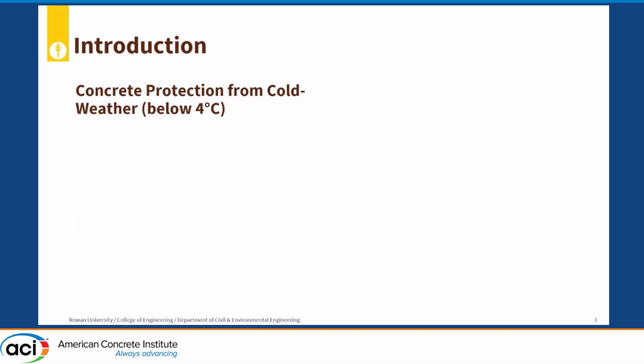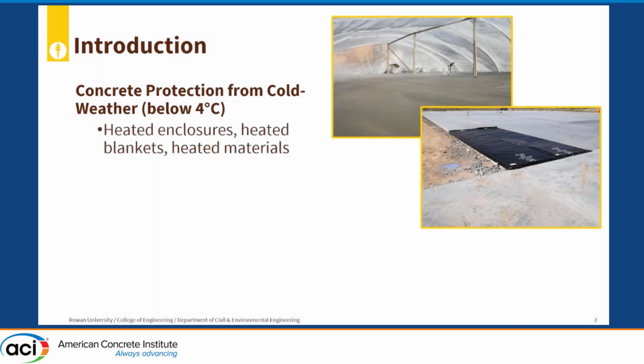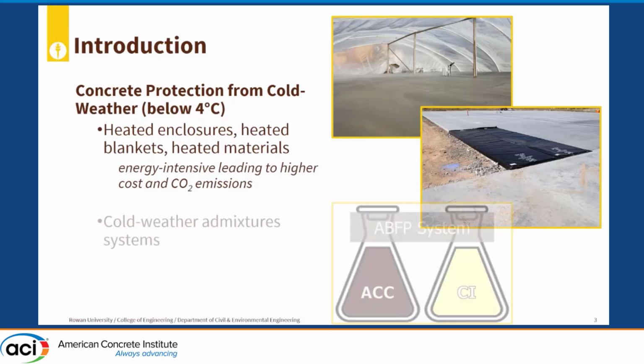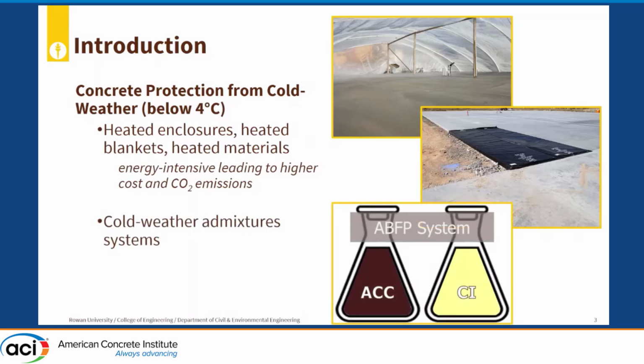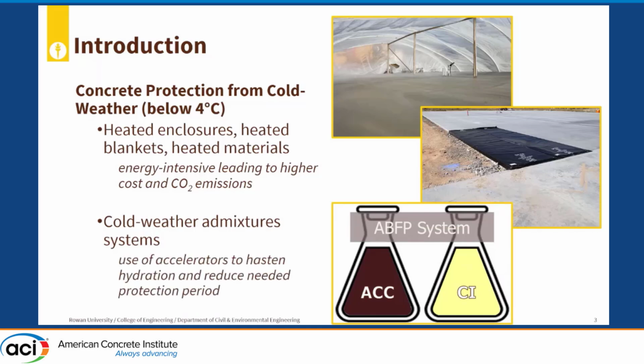When temperatures go below 4 degrees Celsius, ACI requires concrete be protected from cold weather, and traditional methods include heated enclosures, heated blankets, and heating materials. However, these methods are energy intensive, leading to higher CO2 and cost. Our approach uses cold weather admixture systems, or as we prefer to call it, additive-based frost protection system, or ABFP system, that uses accelerators to hasten hydration and reduce needed protection period.